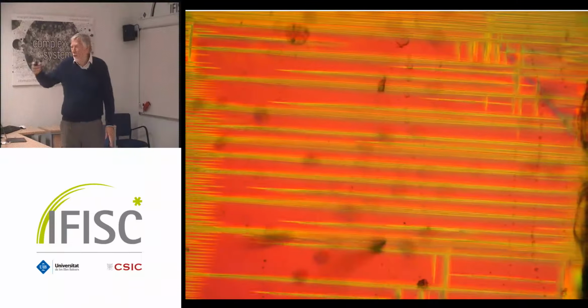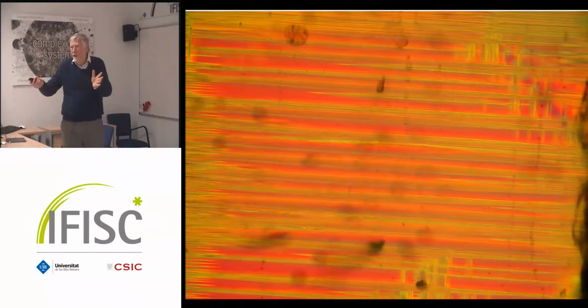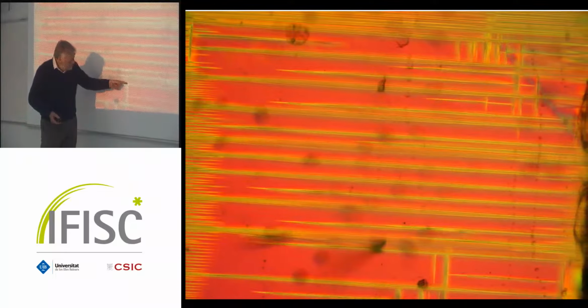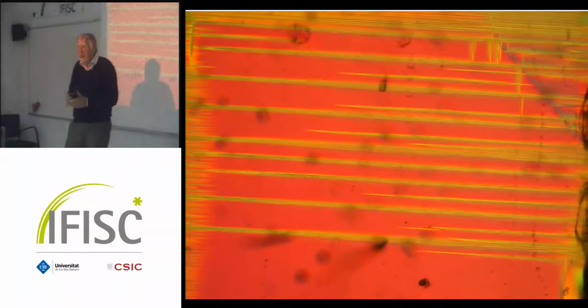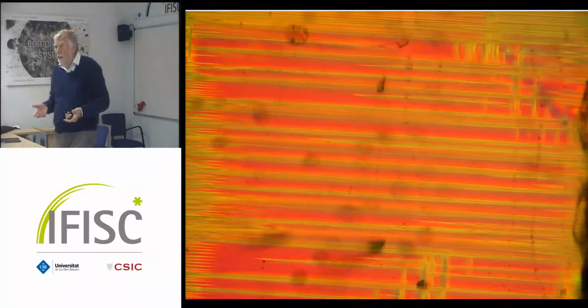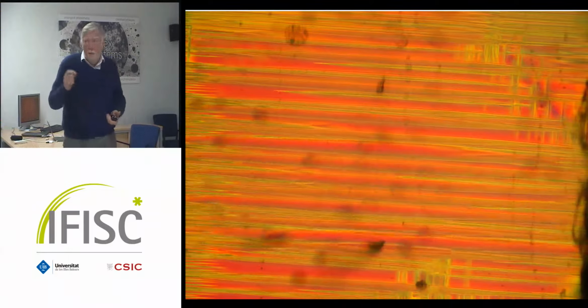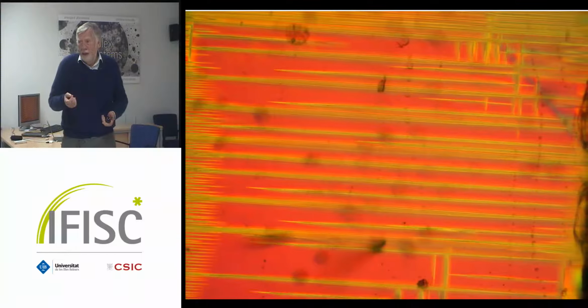It's a high-speed camera, but in fact, this experiment takes about 24 hours. So we make lots and lots of frames, and then just edit it in such a way that we cover the 24 hours. And what you can see are these needles I was just talking about. They're shooting in, and then for those in the trade, you see immediately that you have secondary needles which are perpendicular, and then you have tertiary needles, and quaternary needles, and so you have really self-affine. What is the size? The thickness of the wall is about 2 angstrom, and this size here is macroscopic. I would say 5 micron, something quite standard.